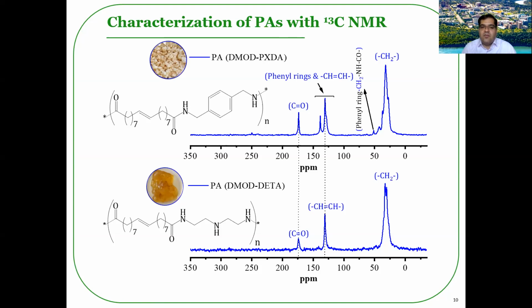A few more peaks in the range of 123 to 142 ppm of the semi-aromatic spectrum were attributed to the aromatic carbon atoms in the phenyl rings of that polyamide. There are some peaks in the range of 18 to 46 ppm of the polyamide spectrum related to the aliphatic methylene carbon atoms in the chain of the polyamides. Another peak at 51 ppm of the semi-aromatic polyamides DMOD-PXDA is related to the carbon sites between the phenyl rings and the amide group of that polyamide.